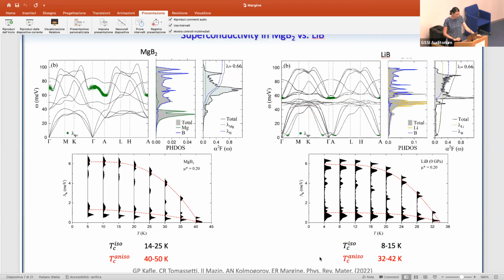So now let me go back to our calculations. Here I'm just showing a comparison with magnesium diboride. In agreement with the previous ab initio studies, we found that the coupling with the boron-boron stretching E2g mode is reduced in lithium boron compared to MgB2. Here this dot shows the strength of the electron-phonon coupling. And as was pointed out by Matteo, this is due to the different dispersion character of the two bands. You can see in MgB2 this band is largely dispersed, while in lithium boron it is way more flat. On the other hand, in lithium boron, we have some coupling that comes from this very soft mode below 10 milli-electron volts.